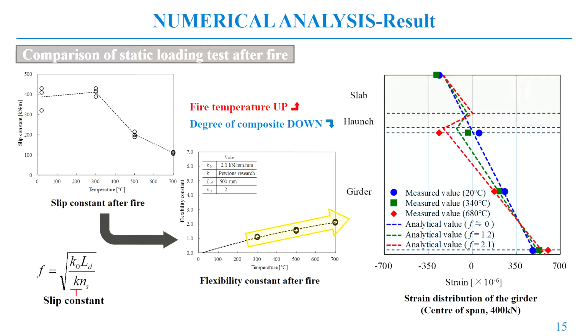Let's move on to the next slide. This slide shows validation of analytical method. These figures show slip and flexibility constants after fire. On the other hand, this figure indicates the strain distribution of the test specimen of static loading test after fire. A comparison between the measured and analytical values of strain distribution show almost the same as the measured values.